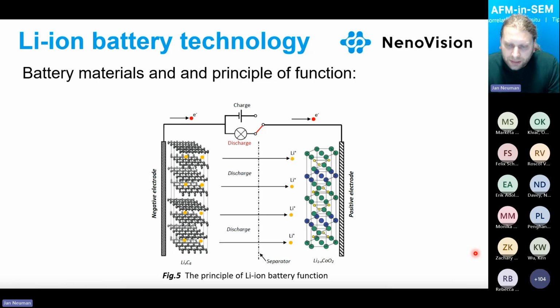The lithium is mainly in the cathode, which is based on lithium metal oxide, usually with metals like manganese, cobalt, nickel. And the anode is based usually on graphite. And the electrolyte is a mix of solvents like dimethyl carbonate, ethylene carbonate, and different kinds of lithium salts.